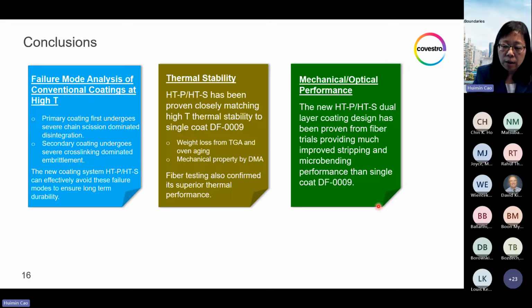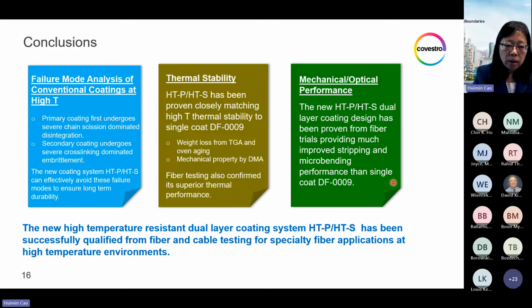And the fiber trials from qualification also confirmed that the new dual layer coating coated fiber provided much improved lower strip force and much better microbending performance than single coat coated fiber. So this new high temperature resistant dual layer coating system, HTP, HTS, has been successfully qualified from fiber and cable testing for specialty fiber applications at this high temperature environment.